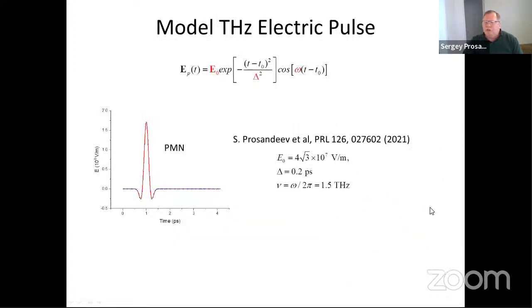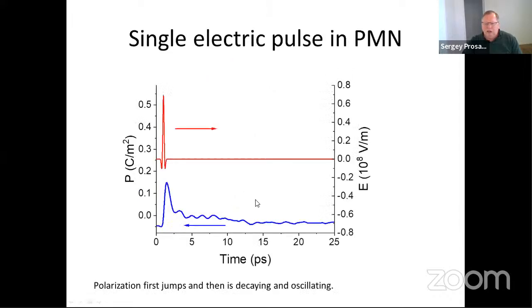Okay, let me switch to the electric pulses in PMN. We used in this calculation the product of a Gaussian function and a cosine, and parameters are shown here. So we applied this pulse to PMN to see the response. And this is the result for one pulse. We see that after one pulse, the polarization first gets some large value and then decays and oscillates. So it reminds me of the study on strontium titanate I showed before. So this behavior is normal.